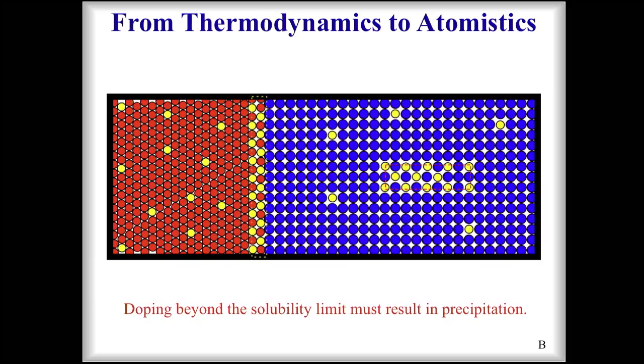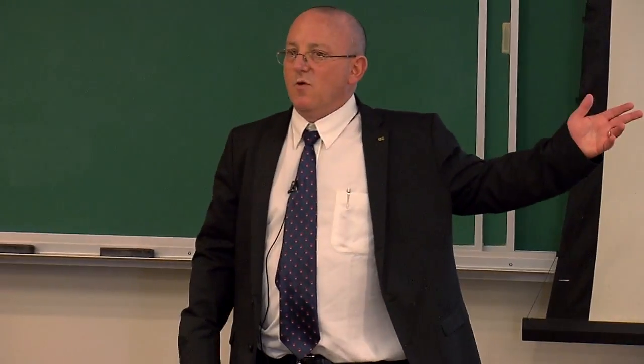If I hit the solubility limit, then I have to precipitate somewhere. Now here, simply because I didn't want to muck up my drawing, I did homogeneous precipitation out in the blue stuff, but this precipitate could form in the red, and of course more likely than anything else, we would have heterogeneous nucleation at the interface itself. But once we're beyond the solubility limit, we must be nucleating new particles, another phase, somewhere.